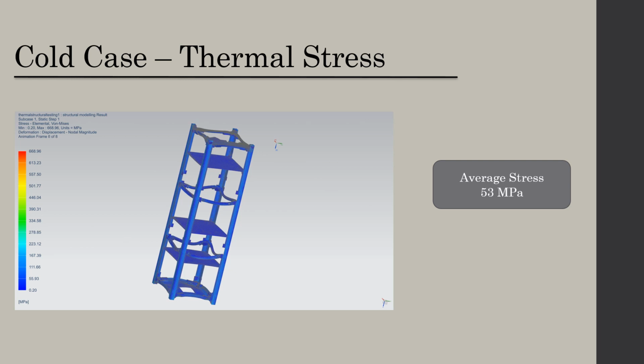Once the temperature profile of the CubeSat was computed using finite element analysis, it could be mapped to a structural model to determine how these thermal loads induce stress, and if the stress is larger than the yield strength of the spacecraft material. As seen here, the average stress caused by the cold case temperatures was about 53 megapascals. The yield strength of aluminum 6061, which is the material of the chassis, fluctuates with temperature. At 100 degrees Celsius, its yield strength is about 260 megapascals, which is significantly larger than the average stress induced.